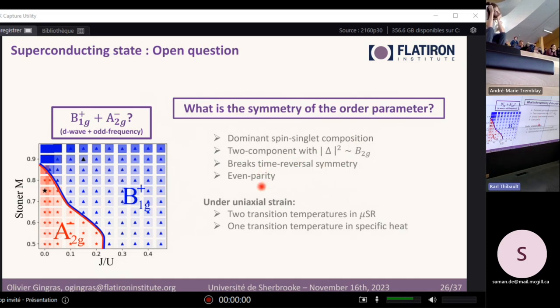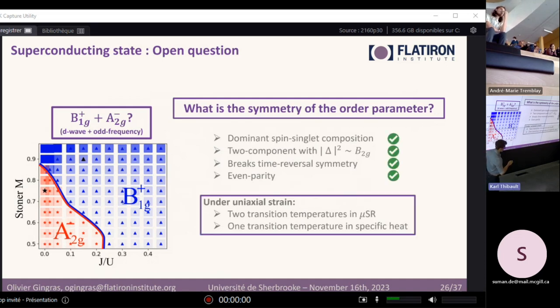And this kind of hand-wavy argument about the specific heat would lead to an agreement between this tension here, because by breaking the symmetry with uniaxial strain, what you could expect is that you first fall into this D wave, which leads to a big signature in specific heat. And then at the lower temperature, you begin to break time reversal symmetry without having a large effect on specific heat. So, yes. So this work really highlights the dominance, I would say, of the D wave in strontium ruthenate. And it proposes a nice alternative for a second component.